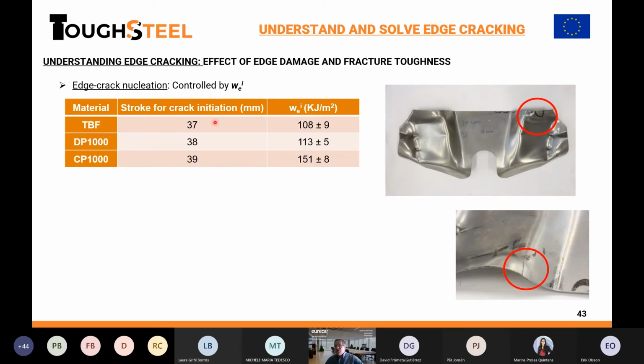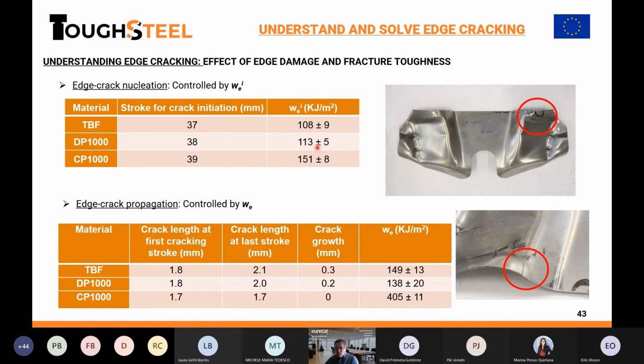And we see that the crack starts depending on the initiation. I mean, this is the stroke where the first crack starts. And you see that because the crack starts to appear, it's controlled by the initiation energy. And it's more or less related to initiation energy. But then these cracks will grow, because if you keep on following with the stroke and you keep on deforming, these cracks will further grow. And these are explained by the total work of fracture.